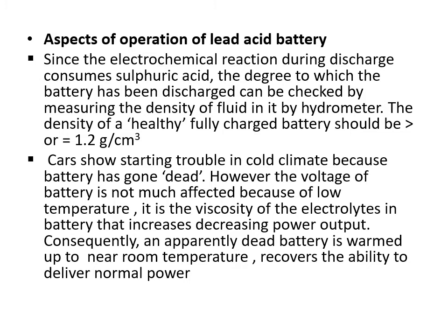Cars show starting trouble in a cold climate because the battery has gone dead. However, the voltage of a battery is not much affected by low temperature. It is the viscosity of the electrolyte in a battery that increases, decreasing power output. Consequently, an apparently dead battery, if warmed up to near room temperature, recovers the ability to deliver normal power.